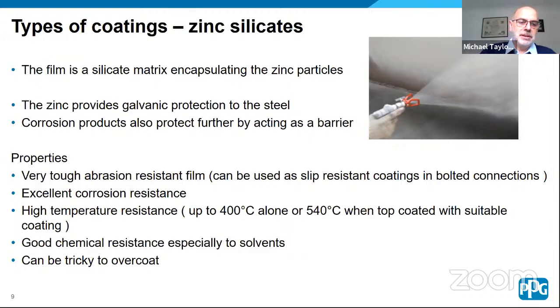The silicates also have very good chemical resistance, especially to solvents. Martin mentioned that you have to watch the pH range between 4 and 12. Outside that range, you can get a reaction with the zinc. But for tank lining, for example, you could use a zinc silicate coating at typically about 75 microns dry film thickness, and it's very good for resistance to solvents, even aggressive chemicals such as methanol.